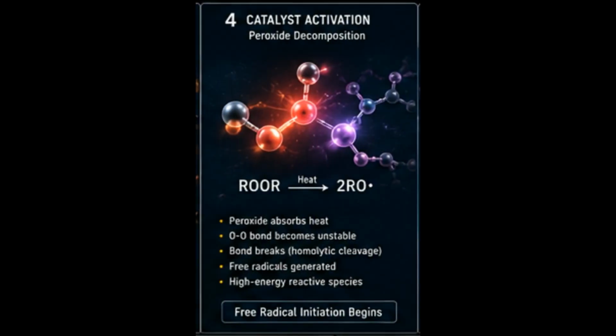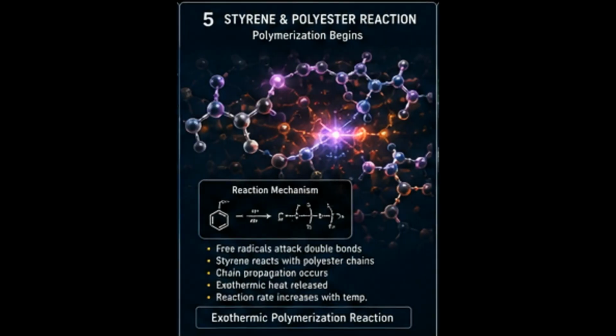Catalyst activation begins with the decomposition of the peroxide. The peroxide absorbs heat, causing the O-O bond to break, which generates highly reactive free radicals. This initiates the free radical reaction. Polymerization begins as the free radicals attack the double bonds. Styrene reacts with the polyester chains, leading to chain propagation. This is an exothermic reaction, where heat is released and the reaction rate increases with temperature.